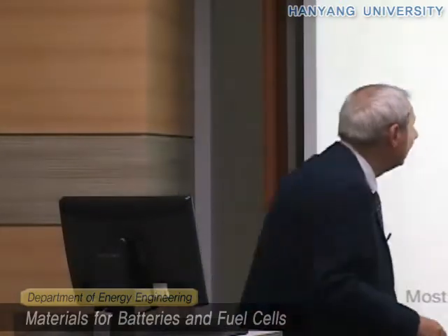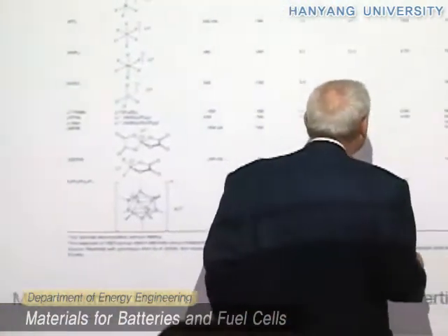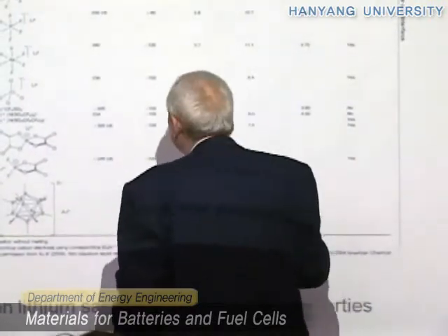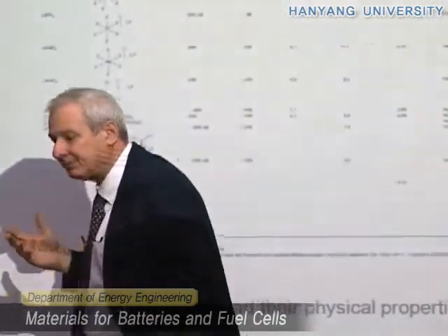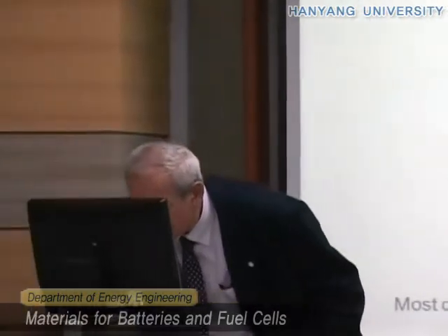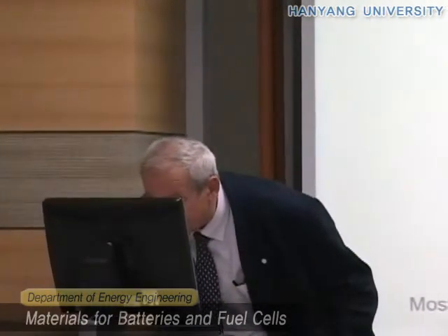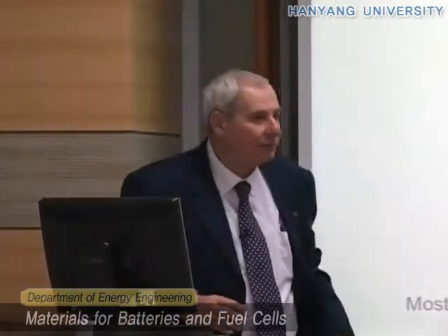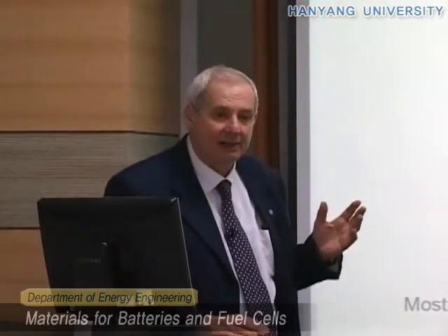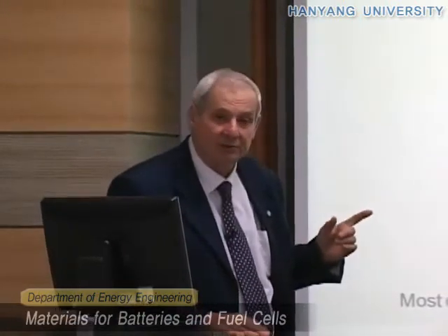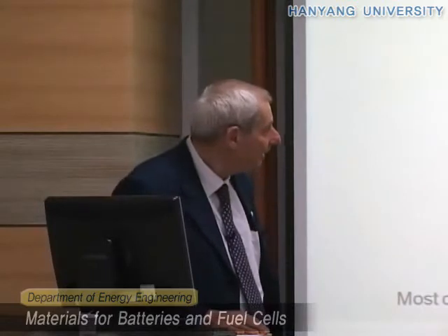So this here, unfortunately, is not very clear. Here is the value. For instance, if we take LiPF6, we see more or less that this value is 4-something, 4.85, 4.65. So that means that up to 4.65 volts, the battery may operate without decomposing the anion.